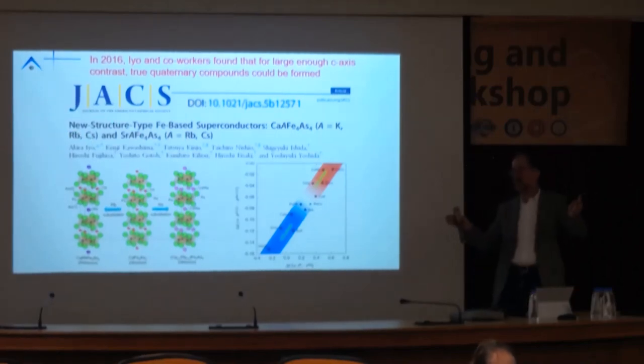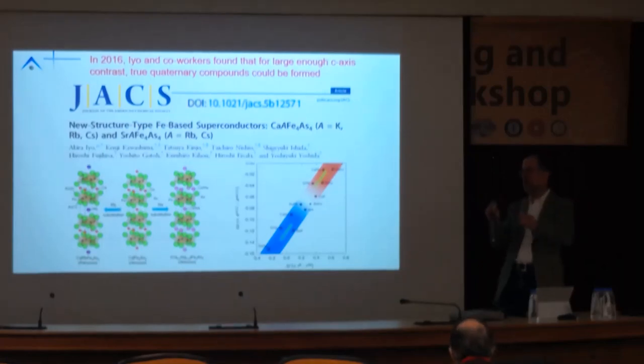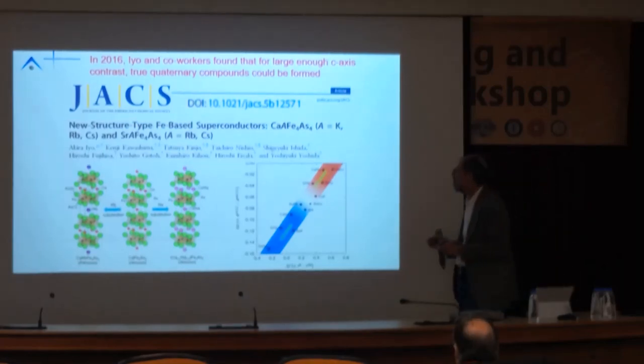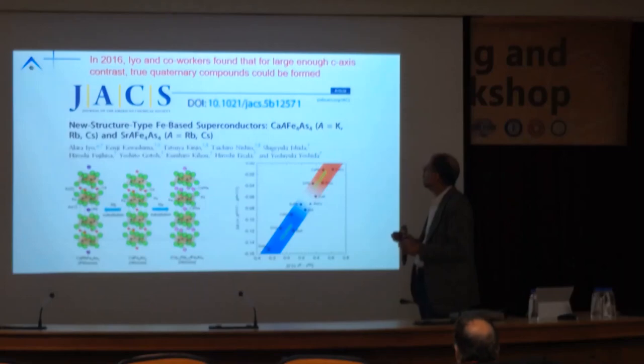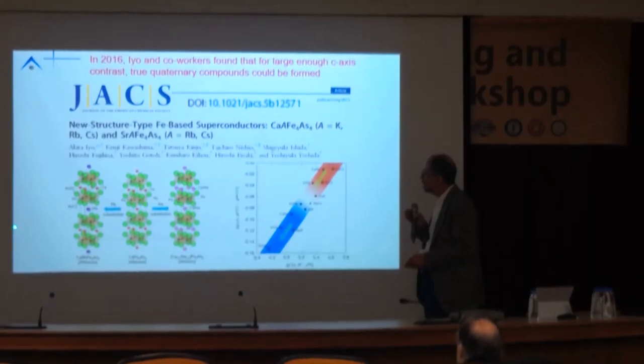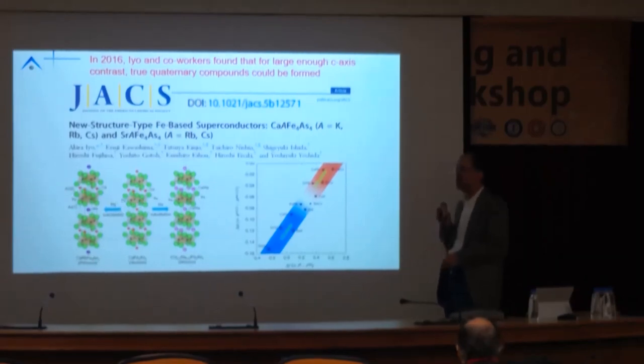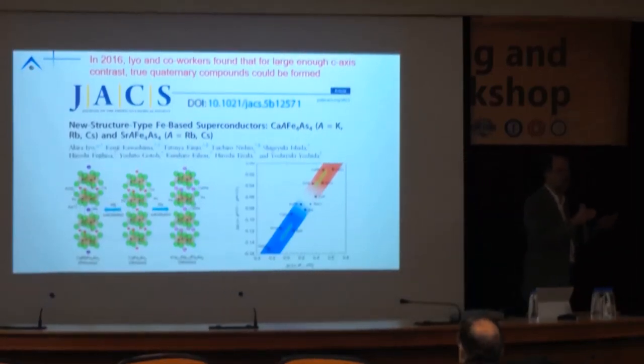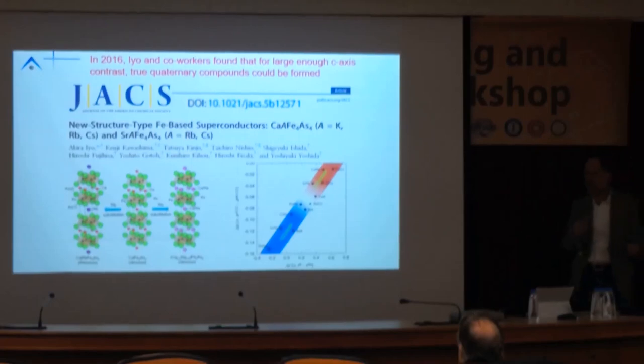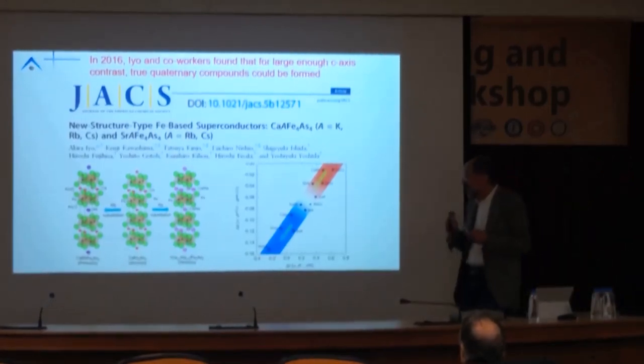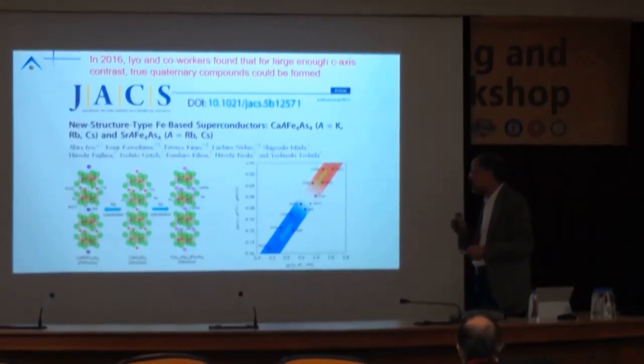in c axis, you could essentially have an epitaxially mediated plane. Instead of having a solid solution, you could end up with a true quaternary. So in the case used in their paper, rubidium and calcium, you could have a rubidium layer, iron arsenic, calcium layer, iron arsenic, rubidium, calcium, alternating along the c lattice. This puts iron in a different point symmetry. It's a different crystal structure, and it actually has very interesting physics.